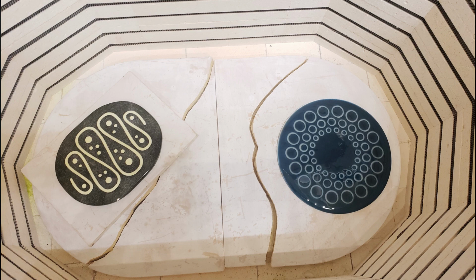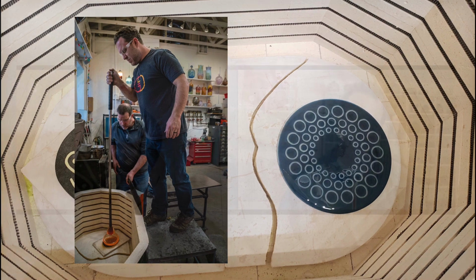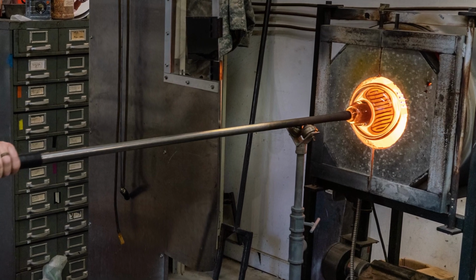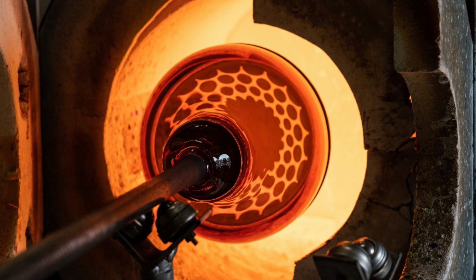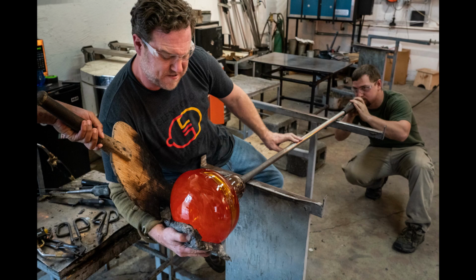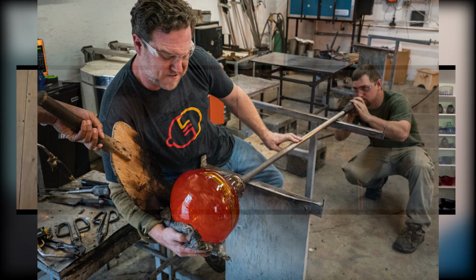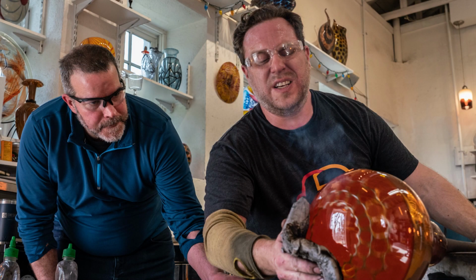We ramp it up for about 12 hours up to about 1,000 degrees, and then we spike it up to about 1060 just before pickup time, so it has a little extra stress relief on the top of the plate, and it helps with the last minute stress of getting that enormous plate from the bottom of a bubble into the furnace. So we run that over to the heat. We start balancing out the temperature and start creating more of an expanded bubble, and pushing the air against the interior bubble into the plate forces those bubbles sealed all around the edges, and we can start shaping the piece as one instead of a bubble with a plate on the bottom.